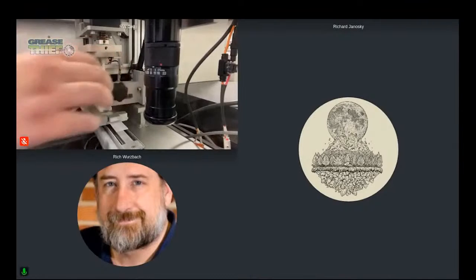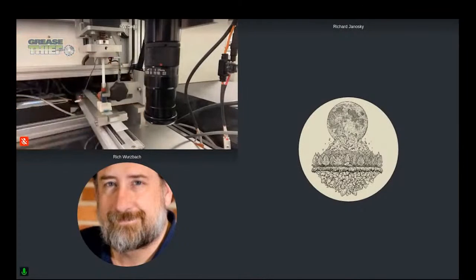Yeah, and there are some limitations here, right? We sometimes find that greases that have significantly hardened, or greases that have a lot of contaminant or wear particles in them, will be unable to undergo a full extrusion, right? Yes, that's correct. Especially grease samples that have larger particles. Depending on where they're at in the grease thief, because as we know, wear and contamination is not 100% homogeneously spread throughout our grease body. If it's right at the beginning, the die extrusion would be clogged pretty quickly, and you might not get a full run. Whereas if the particles are at the end, you might get a full profile extrusion and then the particle effect at the end. But yes, large particles can cause that buildup of pressure, and then it stops the machine to protect the load cell.